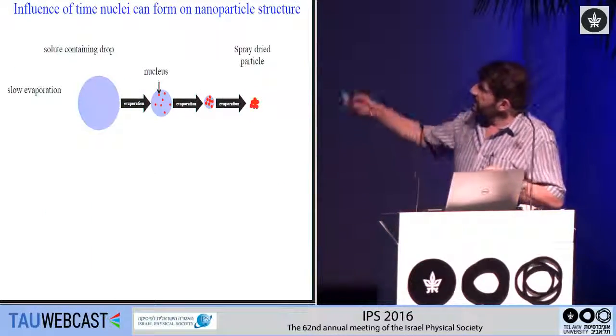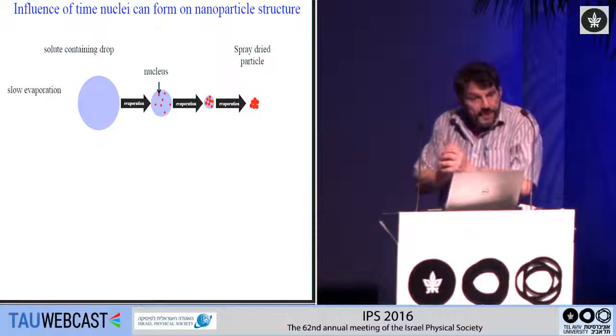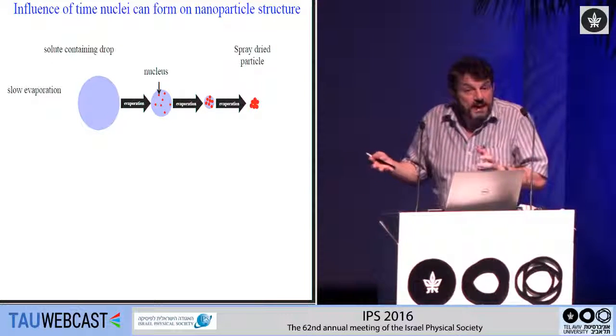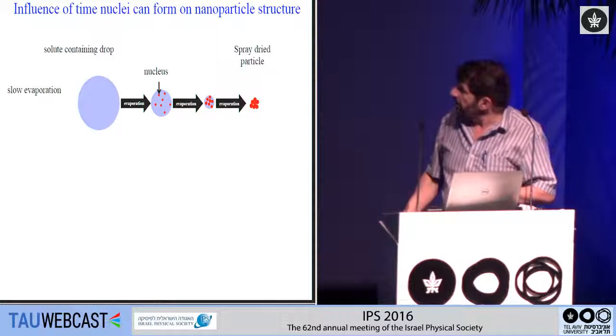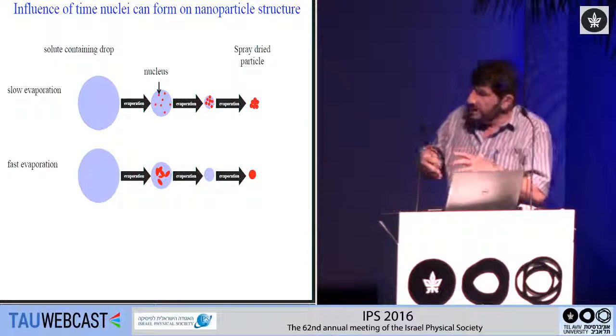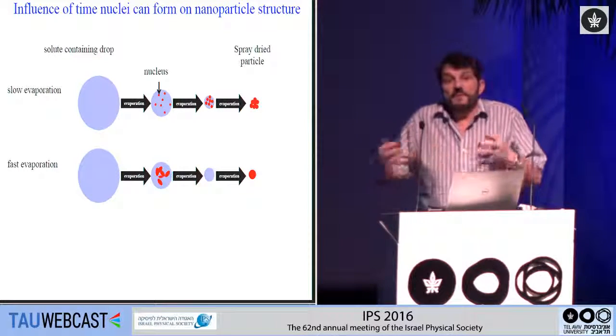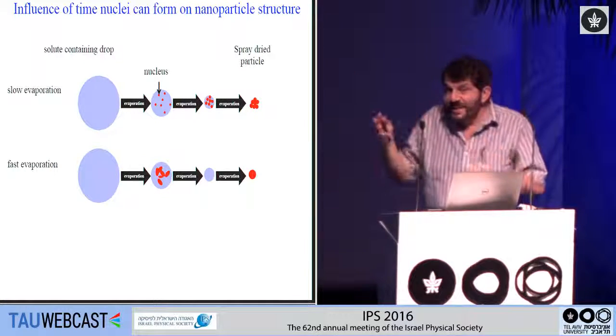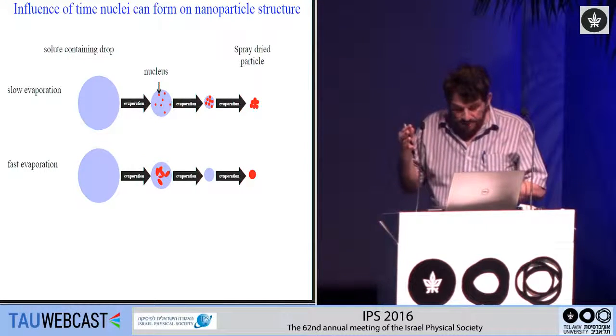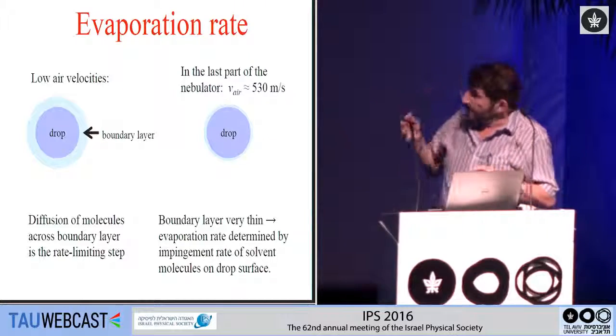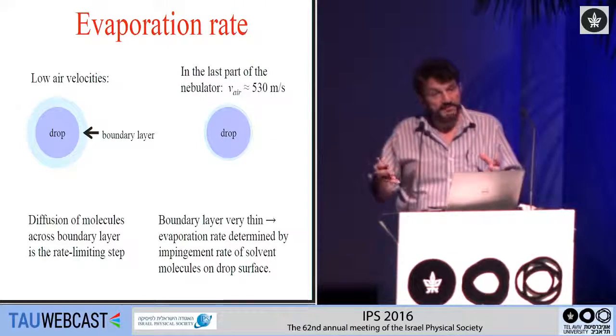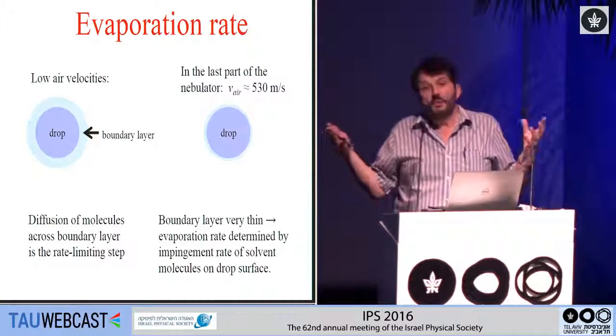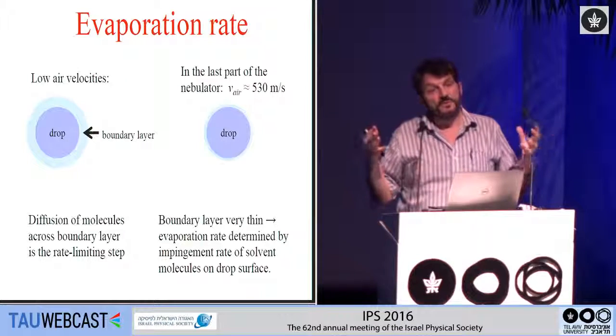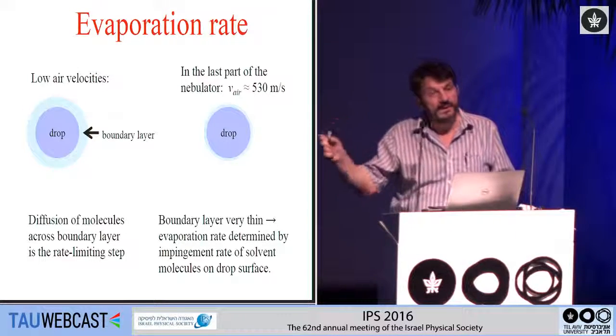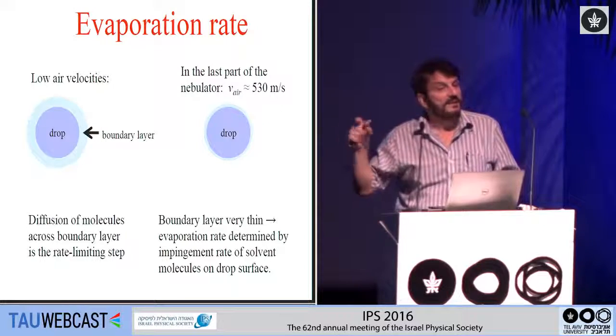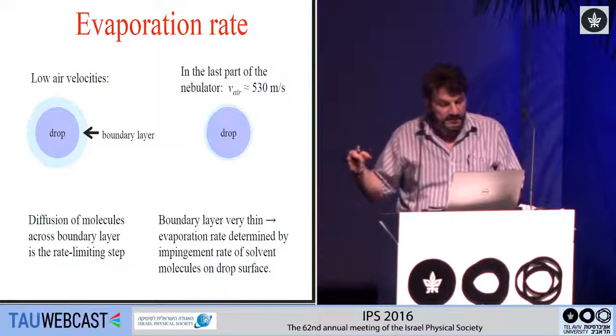Well, remember I said that if you do this evaporation, you would expect still crystallinity to occur. But if you make the drops very, very small, then they're going to evaporate much, much faster. Nevertheless, crystallinity should still occur. So what you have to do is worry also about the cooling effect. You're evaporatively cooling. Well, you can calculate that. Because the flow is so rapid, you can calculate what the boundary layer is, and you can use simple kinetic theory to calculate the rate of evaporation.